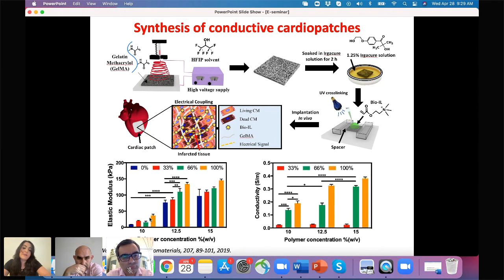Here we show that by changing the polymer concentration that we use to form these patches, and also by changing the concentration of bio-ionic liquid that we added on these patches during photopolymerization, we are able to change the elastic modulus of the hydrogel. In addition to that, we have very good control on the electroconductivity of the hydrogel. As expected, when we add 100% bio-ionic liquid, we had patches with a higher level of conductivity. As we decrease the concentration of the bio-IL, we have a drop in the electroconductivity of the biomaterial. So you're able to change the conductivity of hydrogel in a wider range as compared to the techniques where we use nanoparticles at lower concentration incorporated inside the biomaterials.